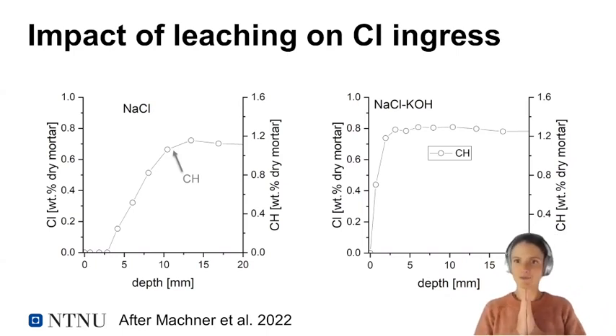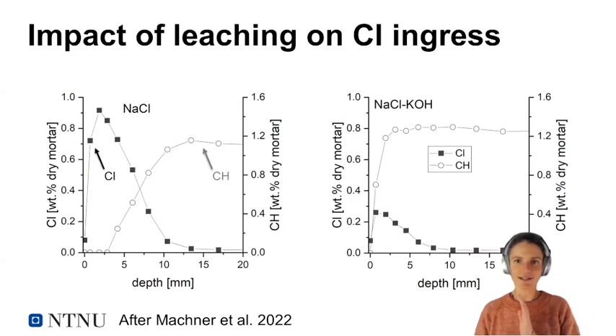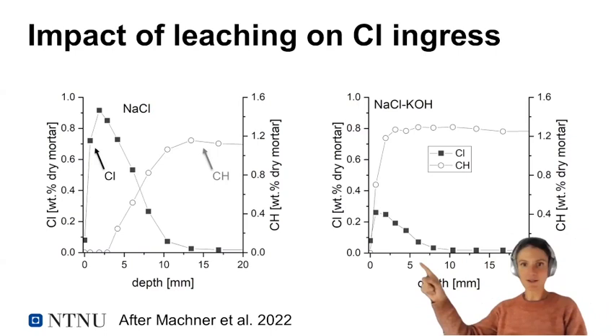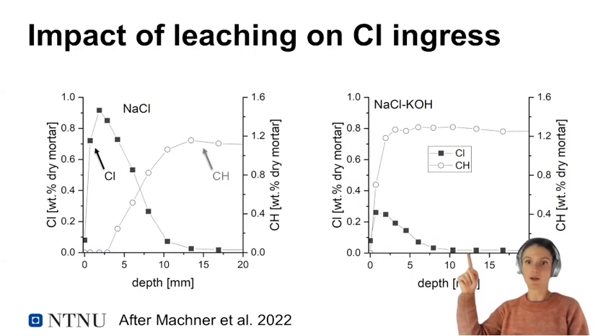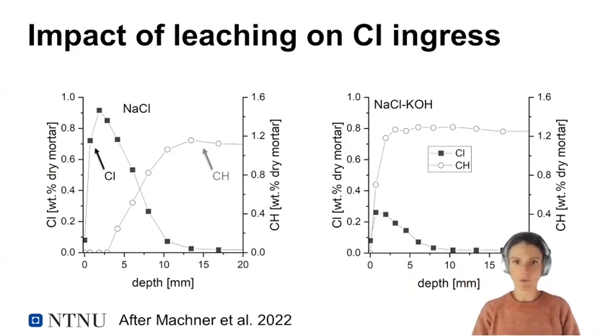So now, what is the impact of these two different levels of leaching on chloride ingress? Here is the chloride ingress profile, and they are very different. If we look at the most leached samples, or the one exposed to sodium chloride, we have much higher chloride levels and further chloride ingress compared to the one here where we've added potassium hydroxide to limit leaching. So it really impacts our chloride profiles.